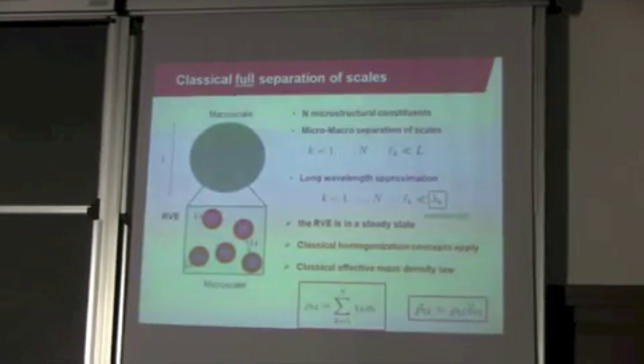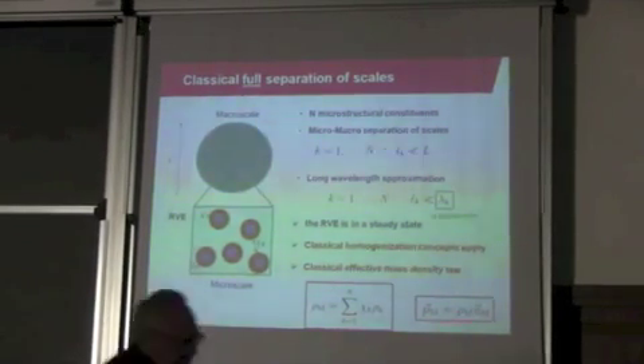If this holds, then one can assume that the microstructure, or the representative volume element of that microstructure, is in a quasi-static condition, and then all classical homogenization results apply, the whole machinery works. Among other results, one can show that the effective mass density is nothing else than the simple averaging of the masses of constituents, and momentum is simply computed as the average density times the average macroscopic velocity.